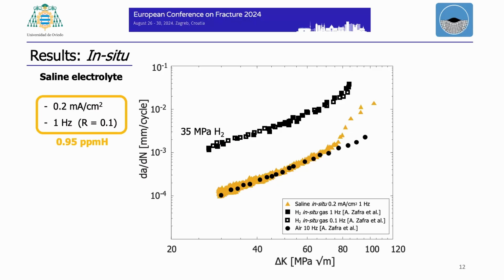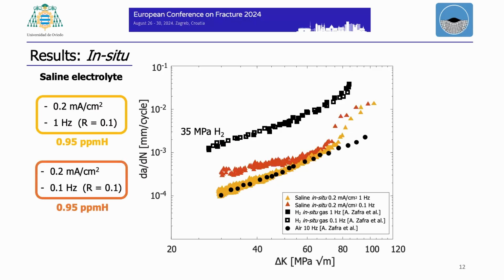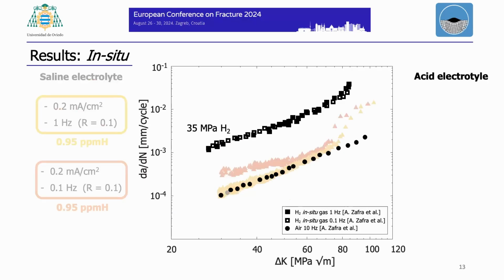So we decided to reduce the frequency. When we reduce the frequency for the saline electrolyte, at the beginning we have a little embrittlement, the growth rate a little faster, but the slope compared with the gas test is lower, and at the end the behavior is the same as the air test. So we decided to increase the hydrogen activity of the electrolyte and start using the acid electrolyte.